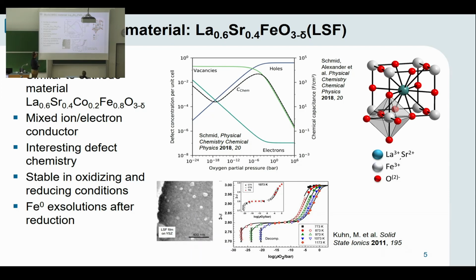And furthermore, when we go to very reducing conditions like dry hydrogen, metallic iron particles appear on the surface of the LSF, which we can see here in such a SEM picture of the surface. And they were also already observed by thermogravimetric measurements, where a constant mass loss at a certain very low partial pressure indicates the onset of decomposition.